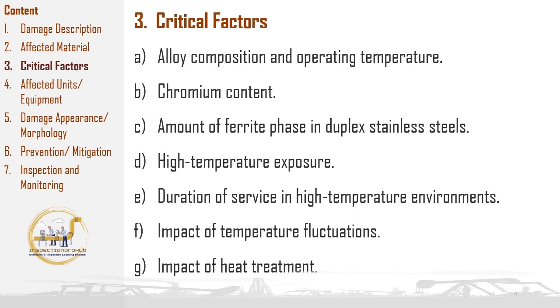This is because such exposure can promote the formation of embrittling phases, such as the alpha prime phase, which compromise the material's toughness and mechanical properties. As a result, equipment operating in this temperature range for extended periods may experience increased vulnerability to brittle fracture and failure. Sixth critical factor is the impact of temperature fluctuations on toughness.